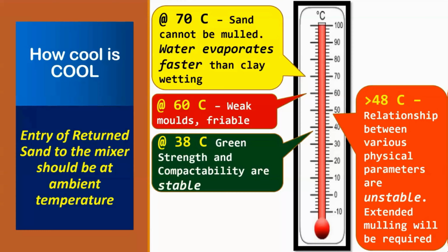because the water is going to evaporate, the bentonite will not be able to develop the bond that is required to hold the sand grains. The obvious result will be the sand grains are not held together in the mold, and then when the metal is poured, they are going to become loose and then get included inside the casting. Particularly if we have some ingates which are very close to this weak part, the sand is going to get eroded and then it will spoil the casting.